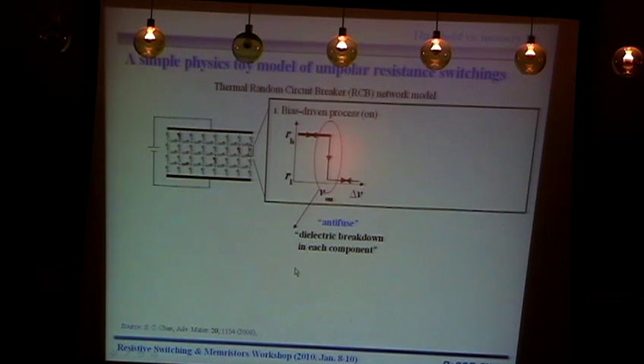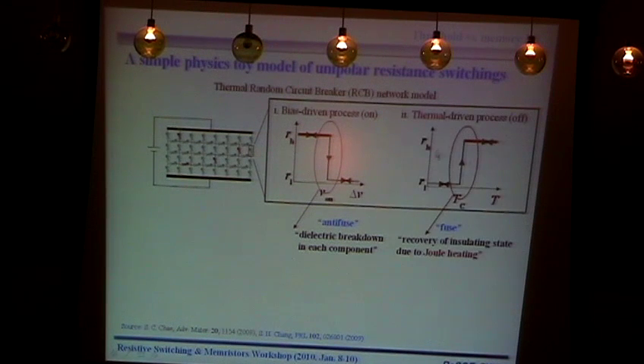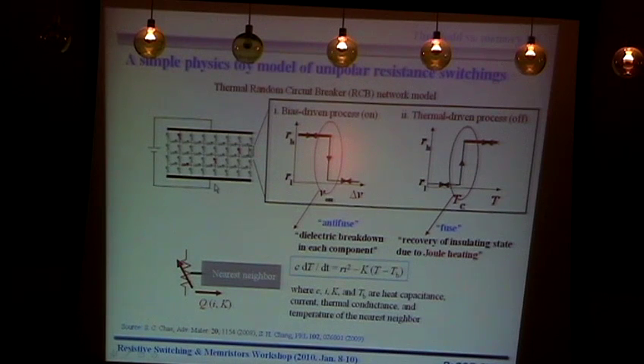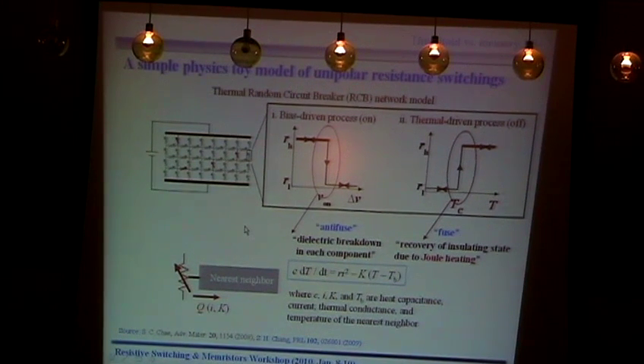So that's the reason we changed one of the switching rules. In here, if it is in the low resistance state, but the temperature goes higher than Tc, then it will change into the insulating state. This is something like a thermal annealing effect. So with this, we have to do two things. We have to calculate the voltage distribution across the circuit breakers, and also we have to calculate the temperature of each circuit breaker. That can be done, it's completely possible.